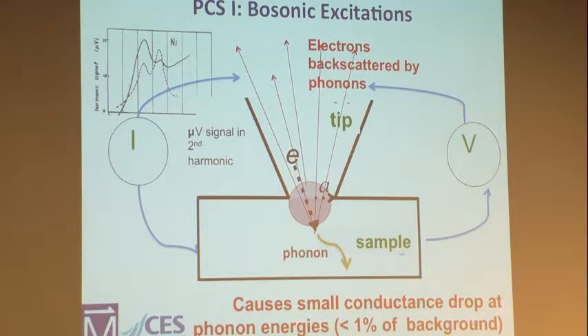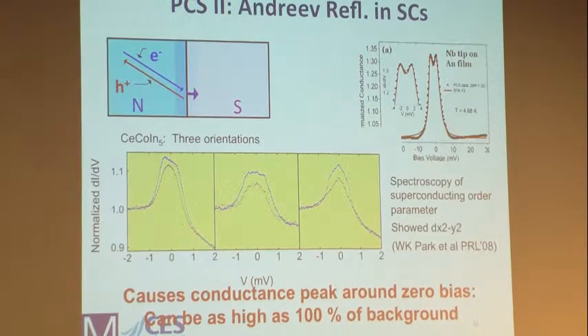So this is always less than 1% of the background conductance, maybe 0.1% or less of the background conductance. So you need second harmonic to pick it up. So the next thing that people used was Andreev reflection. This happened in the 80s, where people started to apply the Bogoliubov-de Gennes equations to interfaces.